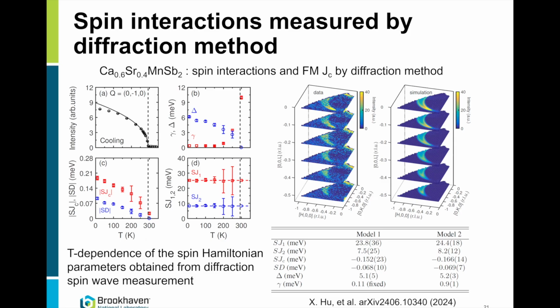The in-plane couplings, which are temperature independent, as you expect, and the effective interplane coupling, which is effective because it determines the ordered spin wave. So anyway, what we obtained is a very complete characterization of our sample in a diffraction measurement.